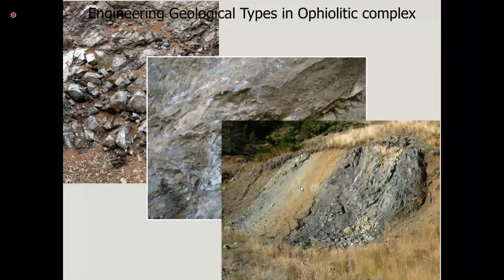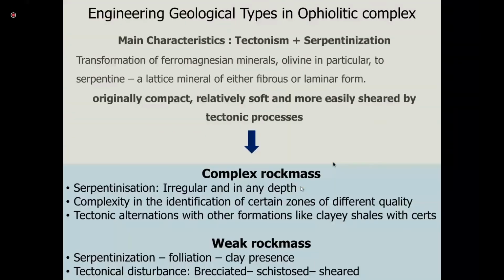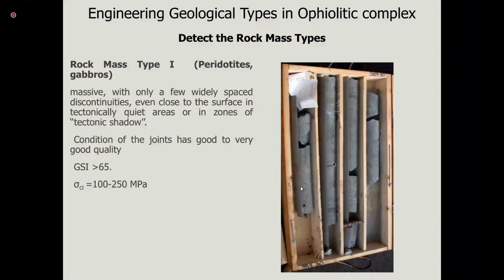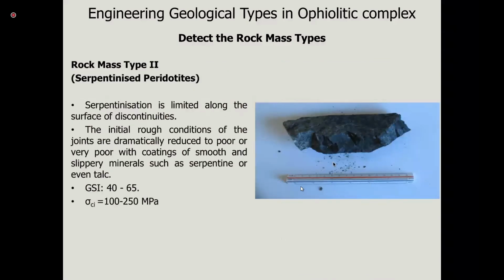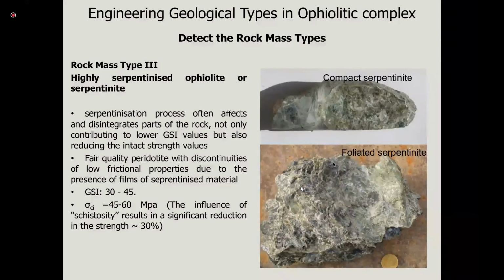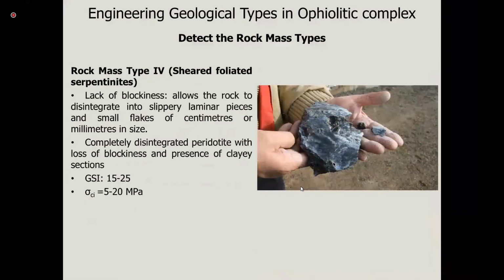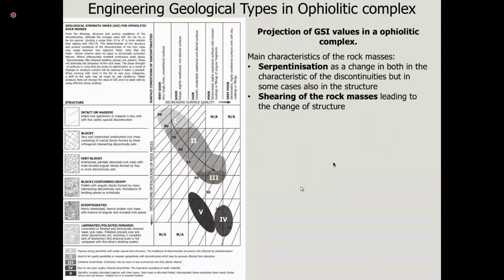You may shift from this blocky rock mass to this heavily serpentinized rock mass to this highly sheared, foliated rock mass. So again, complex rock masses, weak rock masses: from massive peridotites with no serpentinization, very high in uniaxial compressive strength, then again very high uniaxial compressive strength but reduced strength along the shear surfaces, along the joints, due to the serpentinization. Also due to the intensity of the serpentinization, you may have reducing uniaxial compressive strength and mi parameters, and of course the structure is influenced. We can see all this very nicely in the chart. You can see the arrow, the serpentinization intensity, and how it can influence the structure.